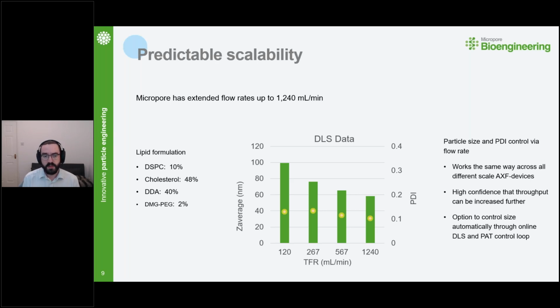Using the same formulation, and in this data showing how we can control the size of the particles that we're producing as well. Essentially what we're actually changing here is the shear that we're applying inside of it, and show that we have this scalability whilst maintaining really narrow size distributions, even decreasing polydispersity index even further as we go on. And because we're using essentially the same membranes inside each of our devices, this gives us that really good scalability across the other devices in our range. Gives you that high confidence that any initial results can easily be scaled up further if you choose to continue on and make larger and larger quantities as are predicted to be needed for these types of materials.